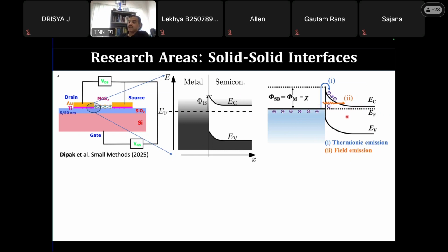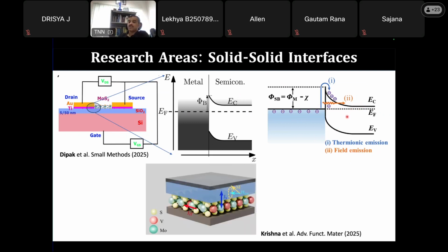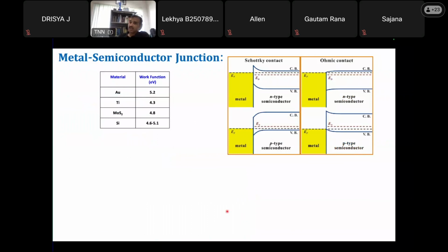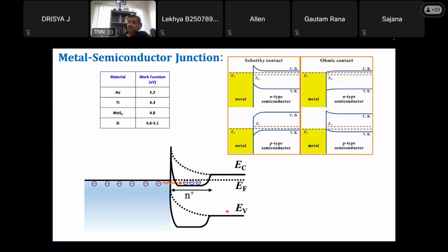So you need to climb the barrier, and this is a real barrier for an electronic device, and that actually causes heat dissipation in the device. When you talk about spintronic devices, this is even worse. If you have such a Schottky barrier, the spins will get relaxed. So this is another very major problem here. So for electronics and spintronics, the Schottky barrier is one of the major concerns. Now you may ask the question.